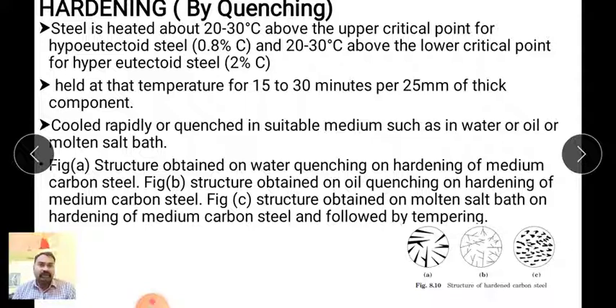Now here we can compare with the full annealing process. The heating above the upper critical temperature and above the lower critical temperature is the same, but the temperature range is different. In the case of full annealing we heat that steel component 30 to 50 degrees Celsius above. Here we heat 20 to 30 degrees Celsius above. This is one difference. The second difference is that in full annealing the steel is cooled slowly to room temperature, but in the hardening process we rapidly cool or quench in a suitable medium such as water, oil or molten salt bath. In full annealing, we cool that steel component to room temperature very slowly in a furnace. Okay, cooling medium is furnace.